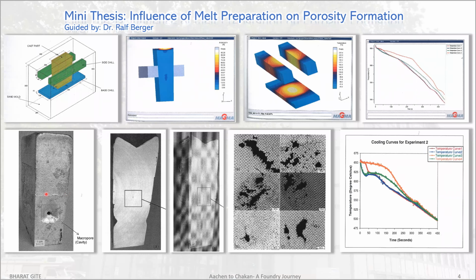And we got the same here, a micro porosity, which was corrected by reducing the distance between the base and side chills, as well as lowering the pouring temperature to get rid of the hotspot in the central part. The melt preparation we did in three to four different formats. The first one was the clean melt with argon to avoid contamination of hydrogen and oxides. The second one, normal melt without any treatment. The third one is the more impure, dirty melt enriched with hydrogen and oxides.